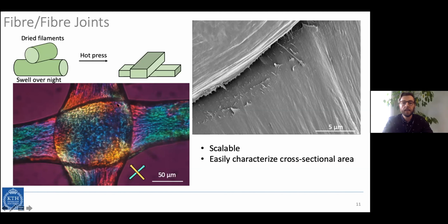The other nice thing about this technique is that we can measure the interfacial area of the joint and use that to understand the strength of these individual joints based on interfacial area. If we look a little closer in the SEM, we can see individual CNF filament fibers included in the joint, and some of them have actually been pulled apart. So we have enough adhesion between these two filaments to pull apart individual CNF fibers.